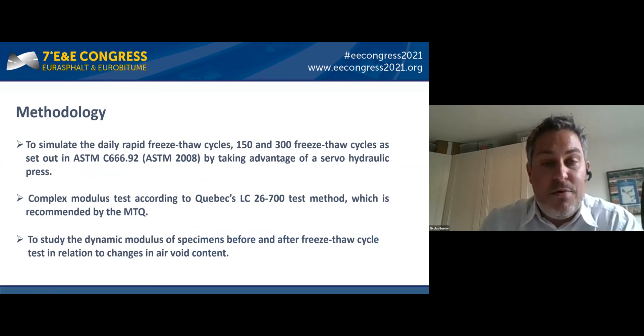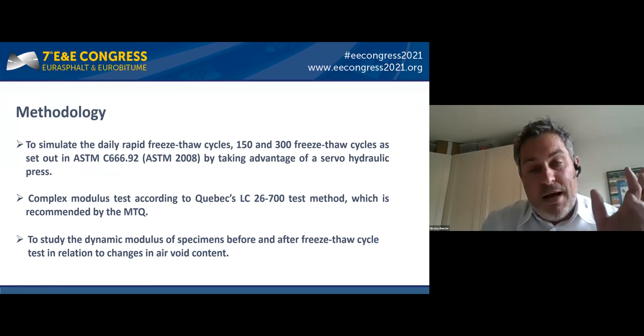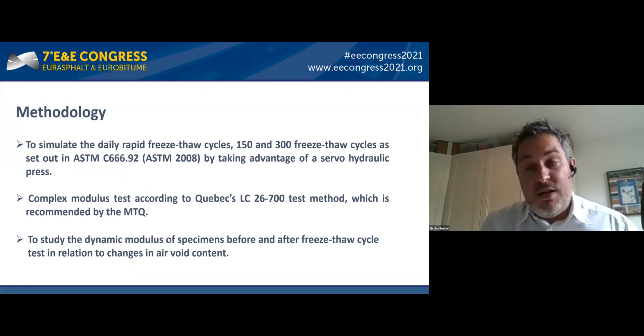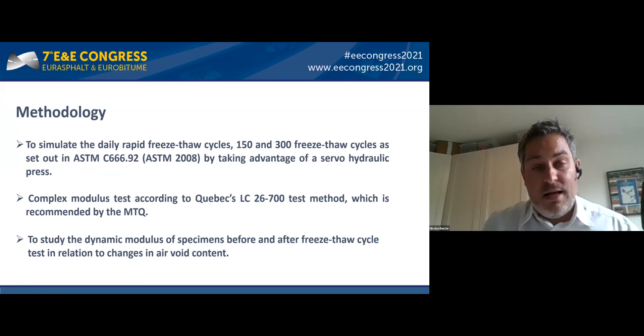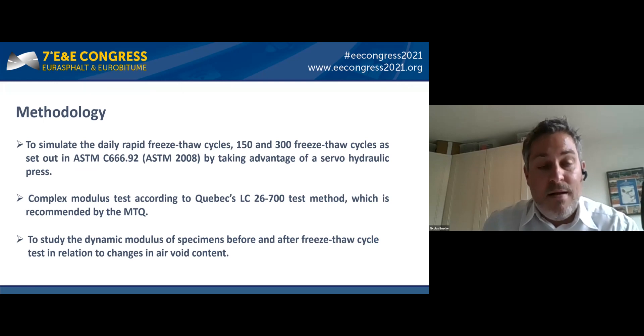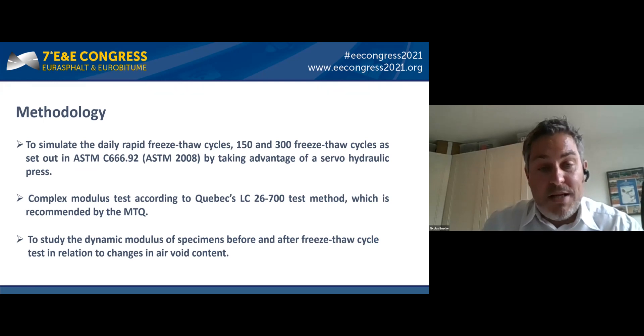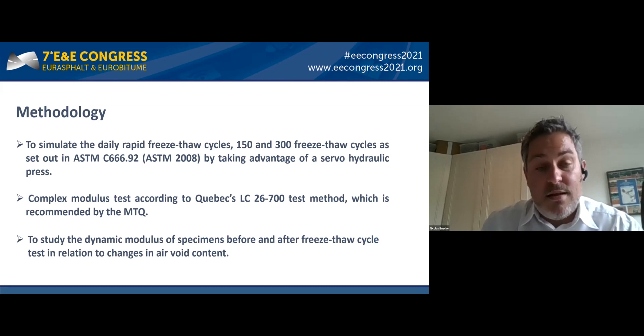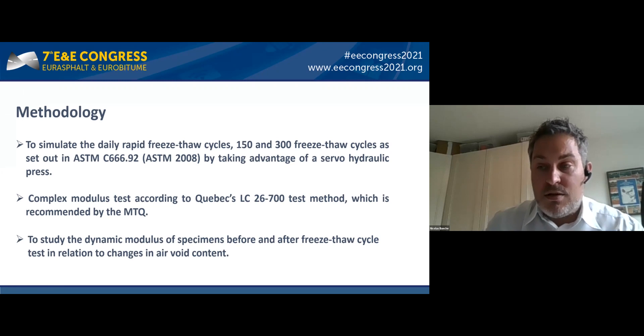The methodology is quite simple. First, we simulate daily rapid freeze-thaw cycles by applying 150 and 300 freeze-thaw cycles as set out in the ASTM method. Then on the samples we perform complex modulus tests according to Quebec's test method. Finally, we study the dynamic modulus of specimens before and after freeze-thaw cycle tests in relation to changes in air void content.